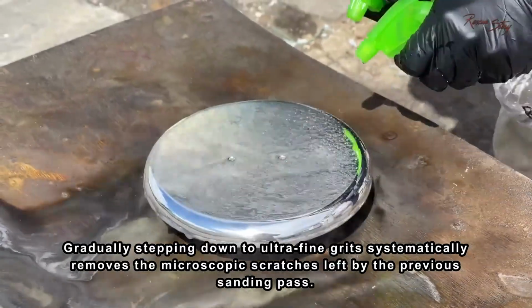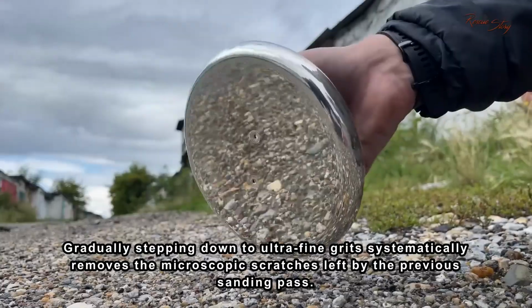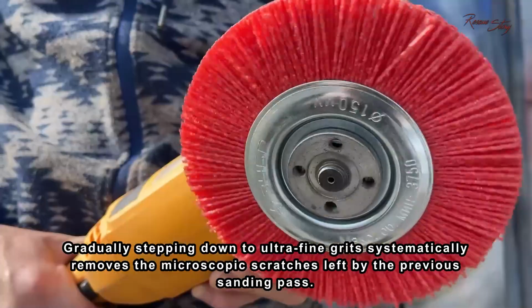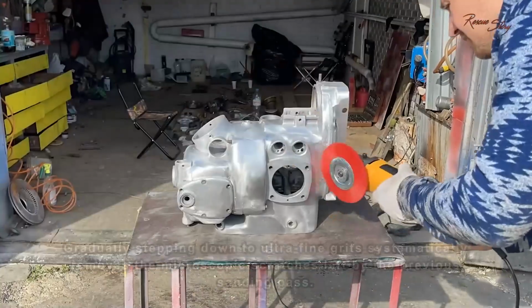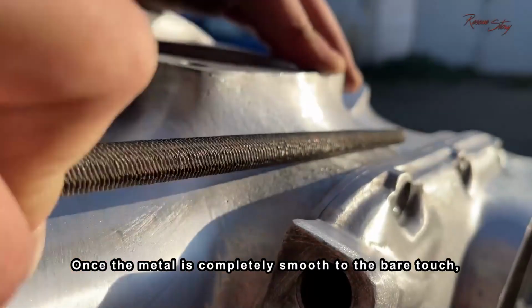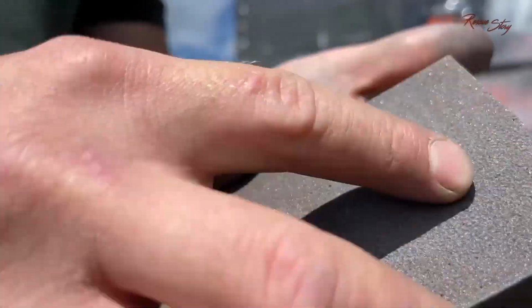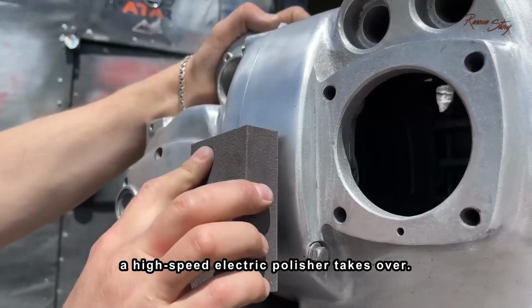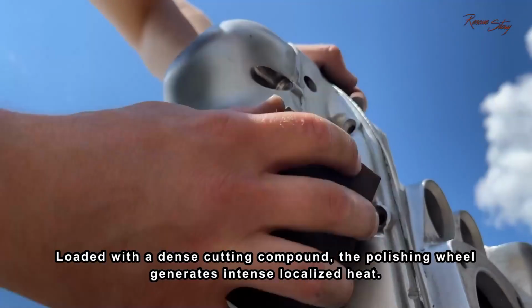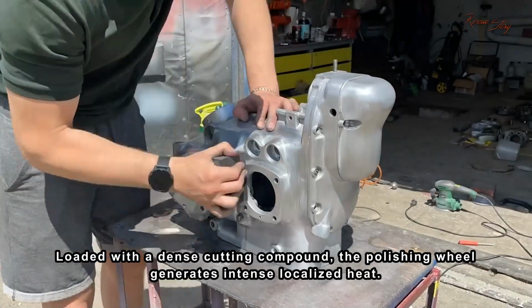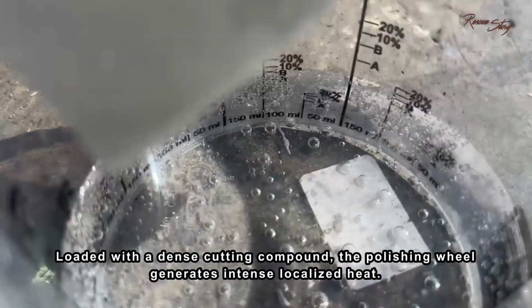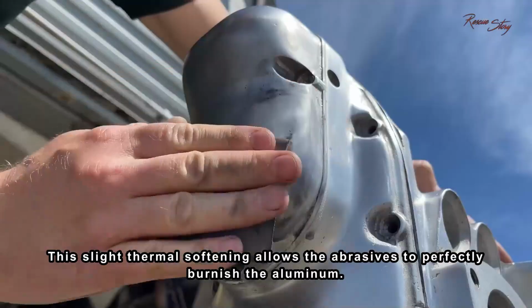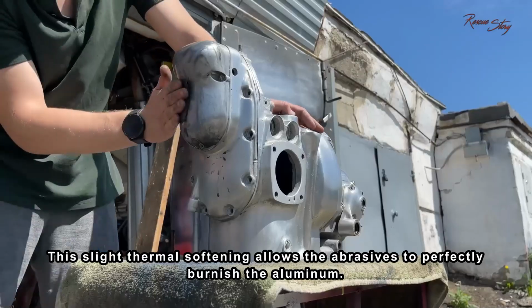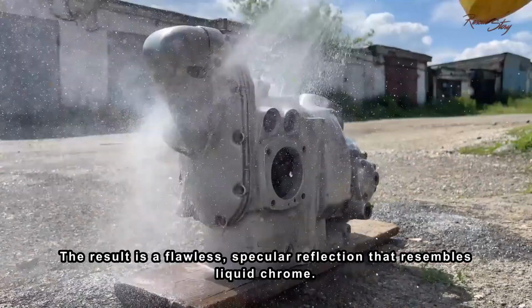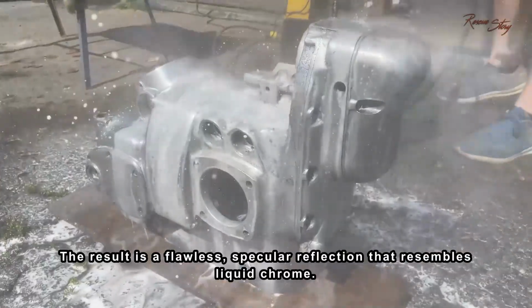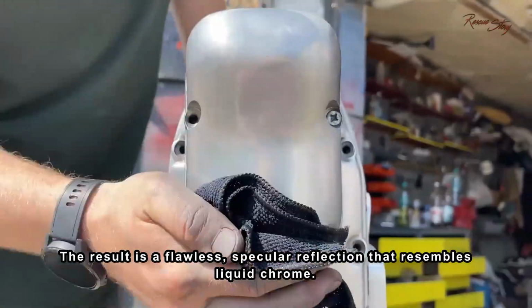Gradually stepping down to ultrafine grits systematically removes the microscopic scratches left by the previous sanding pass. Once the metal is completely smooth to the bare touch, a high-speed electric polisher takes over. Loaded with a dense cutting compound, the polishing wheel generates intense, localized heat. This slight thermal softening allows the abrasives to perfectly burnish the aluminum. The result is a flawless specular reflection that resembles liquid chrome.